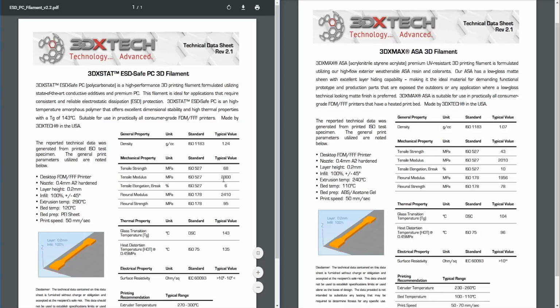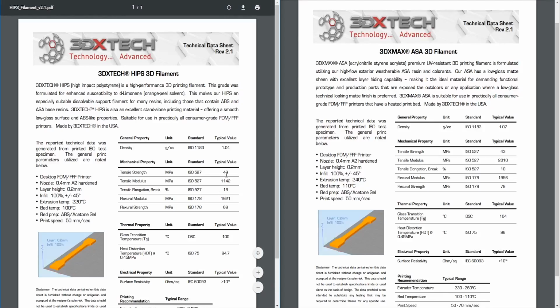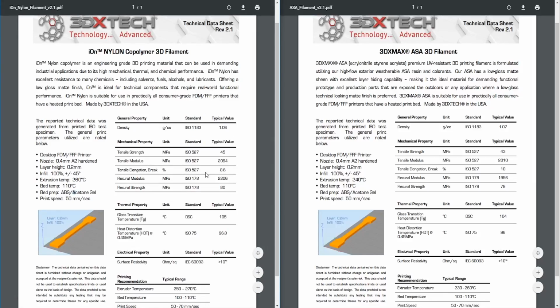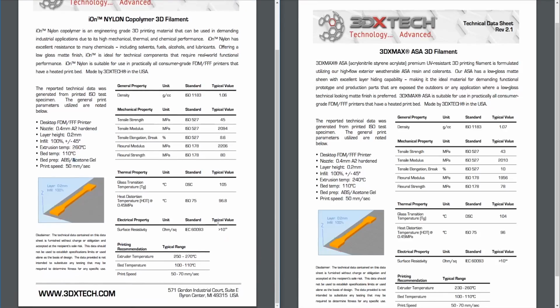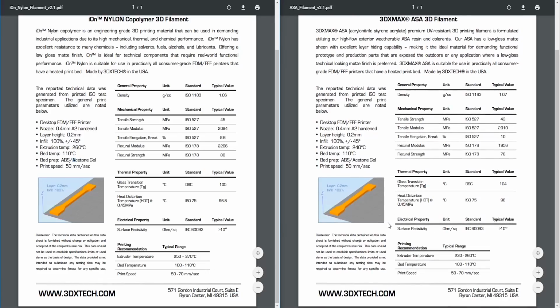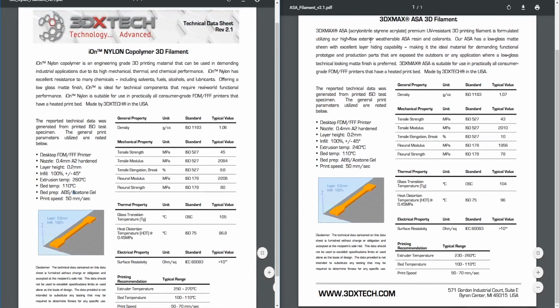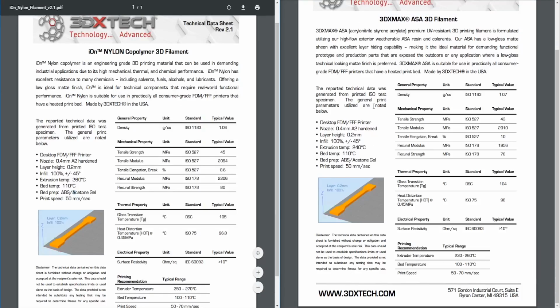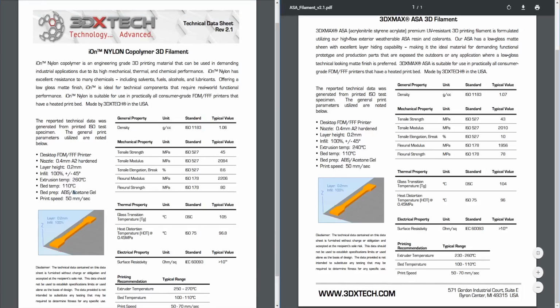ESD polycarbonate, boom, higher, higher, a little bit lower, higher, higher, quite a bit higher. Yeah. HIPS, ooh. And it's almost right on with HIPS and better in a few spots. HIPS is getting beat on. Here, this is going to be pretty close, but with the higher print temperature and similar stability, I would go with the ASA and also the UV. So I mean, this also probably takes on water quite a bit.